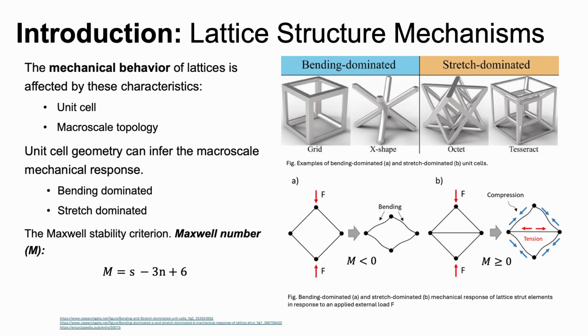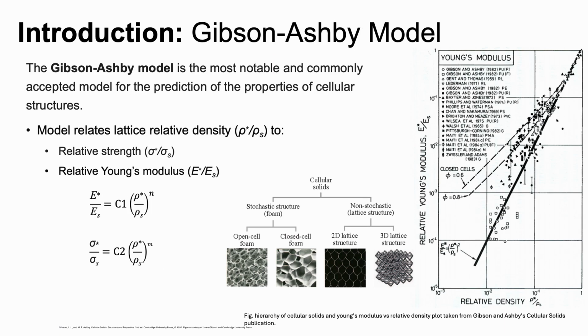If the number is below 0, it means that it's a bending dominated structure because after load is applied, the struts bend because of lower nodal connectivity. When the number is equal to or higher than 0, then it means it's a stretch dominated structure. That means when load is applied, it actually produces tension between the middle of the nodes and compression from the outer nodes, causing this to be a stiffer type of lattice.